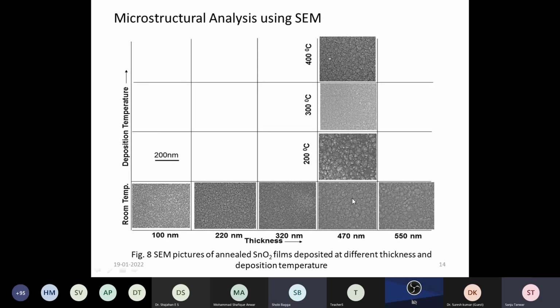Now we go to the microstructure analysis. Microstructure is nothing but scanning electron microscopy. Here we can see that when we increase the thickness of the film, our grain size is slightly increasing. These are the grains which I showed you earlier, how the oxygen comes into contact with them. Grain size is increasing as we increase the thickness. We have optimized this. Later on, you will understand why I have kept the thickness at 470 nanometer.